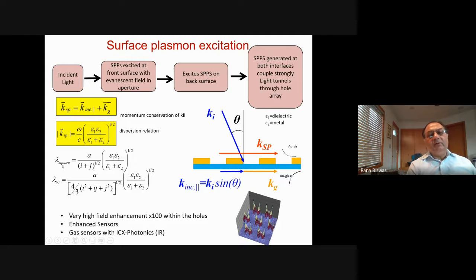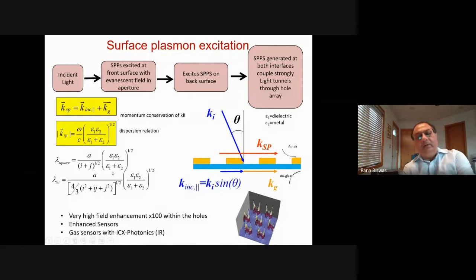And you can see that the wavelength of the surface plasmon is a function of the different orders of diffraction. And in the lowest order, it is very close to A. And here, epsilon 1 is the dielectric, and epsilon 2 is the dielectric function of the metal, both of which are wavelength dependent.